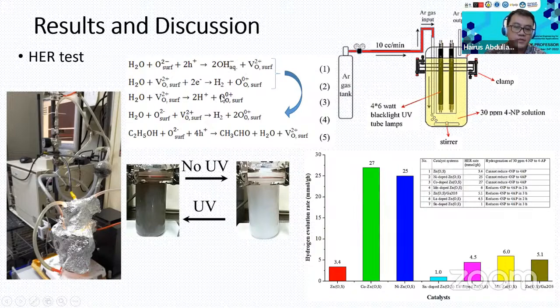So by using the Kröger-Vink equation, we have seen that there is a defect, because this catalyst is prepared at a low temperature, right? The defect is an oxygen defect. This will be involved in the reaction and form oxygen vacancies. The oxygen vacancies become more and more during the reaction. That's why, when more oxygen vacancies form, the color changes to black.